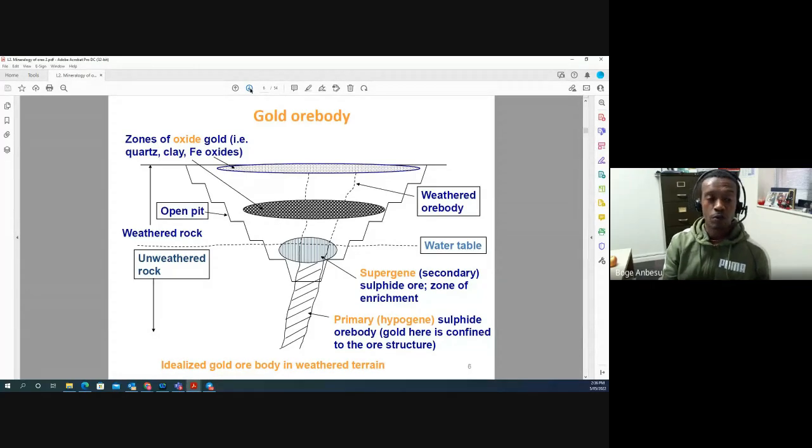If someone was doing open cut mining, for example, typically in the first, say, 40 meters or so, we are looking at that oxide zone. Usually the gold is coarse grained, and therefore I wouldn't worry too much about how you process it, because processing shouldn't be complicated at that stage. The problem is this zone is not very thick. It's probably going to last a couple of years. After that, you have to go deeper, and therefore you have to think about how the ore body changes as you go deeper and deeper.